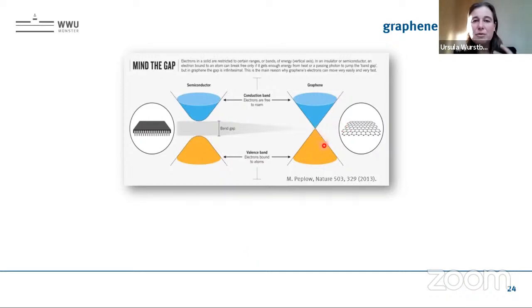If you would like to build a field effect transistor, it's always important that you can reliably turn it off. Turning it off means you have the Fermi level in the band gap: with an electric field, with the gate voltage, you tune the Fermi level such that it lies in the band gap where you don't have an allowed state. And with that, the resistivity of the structure goes high. There's no current flowing, or almost none. And as soon as you tune the Fermi level into one of these bands, conduction band or valence band, you get again a high conductivity.